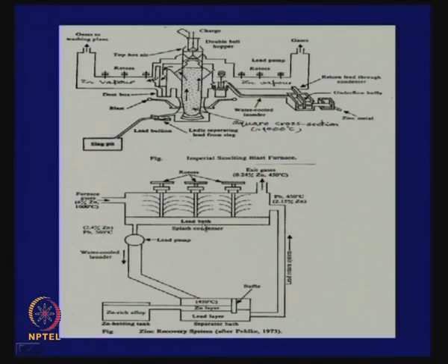You are taking out lead with 2.4% zinc, a bit of zinc separates out, some zinc is left behind, then it is recirculated. In that process, gradually you get a zinc rich alloy, and the lead is continuously recirculated. So, it goes to a zinc holding tank. It is all based on control of the temperature.